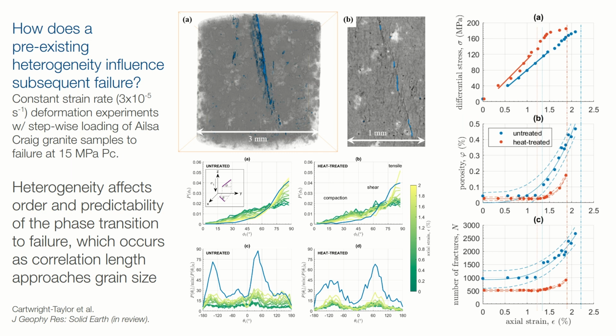This is a paper which should actually be in press by now, or pretty close to, where Alexis has studied the damage evolution in Ailsa Craig granite, and essentially she was comparing the effect of introducing heterogeneity into the sample prior to deformation and seeing what that does. You can see here it gives you a flavor of the sort of images we could acquire at Soleil. These images are now a few years old, and we have since acquired much better ones, but from this data we can follow the porosity evolution here on this hand side, where we compare of course the crack porosity and see what they do throughout the experiment.